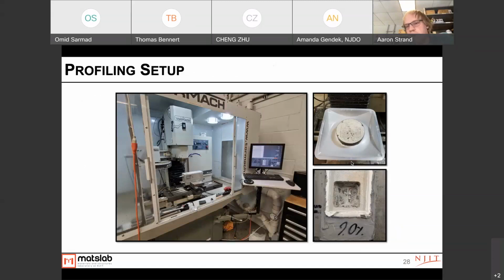And on the right, we can see what a core looked like during the profiling testing to extract the powder. We kept a tray around the outside of it in order to collect any dust that was ejected from the bit. And on the bottom, we can see one of the laboratory specimens and what it looked like when it had reached reinforcement. It's kind of hard to see in the image, but there was a little bit of corrosion present at the reinforcement in the cracked specimen when we had reached the reinforcement.